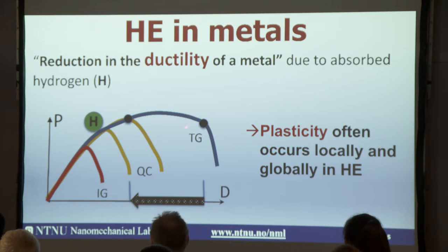The fracture surface will shift from transgranular to quasi-cleavage. That's a mixture of cleavage and plastic features. If you charge the hydrogen more, we will have an intergranular fracture. One thing I would like to note, despite embrittlement, that's a brittle fracture, plasticity often occurs locally and globally in hydrogen embrittlement. So you may ask, what's happening? What are the embrittlement mechanisms? So what happens here?